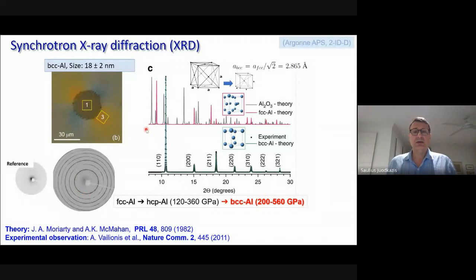unexpected, because what we thought that we would see would be some strange phases of sapphire. Sapphire is the gray lines, and so we thought we would see some changes of those lines, that they would be pushed out of their positions because of immense pressures. But no, this experimental result is shown here. And this corresponds to a very simple cubic structure. And that cubic structure, again, is not usual, because this corresponds to body-centered cubic aluminum, which we don't have around.